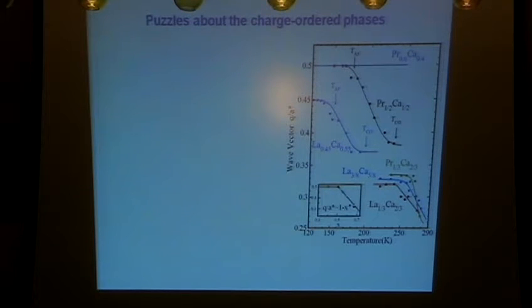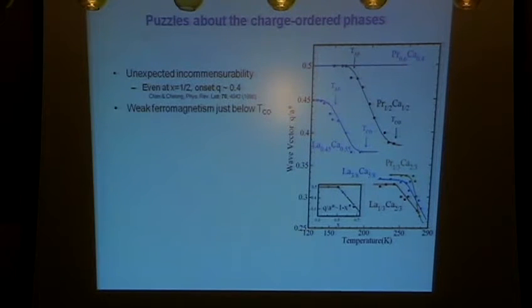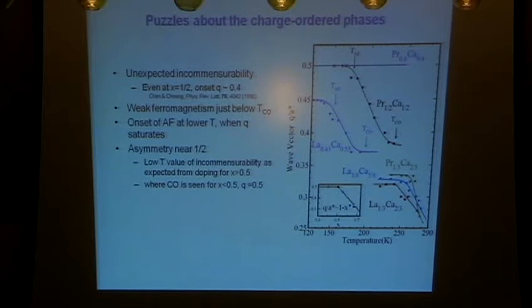Another slight quirk, however, is that if the doping is greater than half, that's what happens. If the doping is less than half, in cases where you still see charge order, the periodicity, however, is not equal to the doping. It's actually a half. So the wave vector has this dog's leg. It goes like 1 minus x, as you would expect at low temperatures, and then it kinks. So a number of oddities about this. We have an unexpected incommensurability, there's weak ferromagnetism, and there's this asymmetry near a doping of a half.